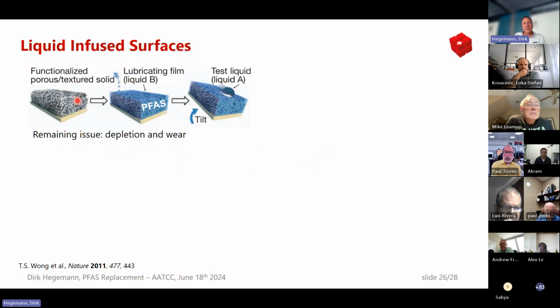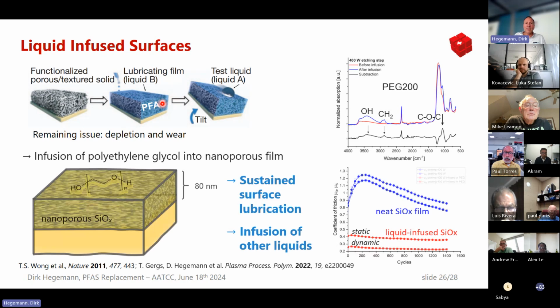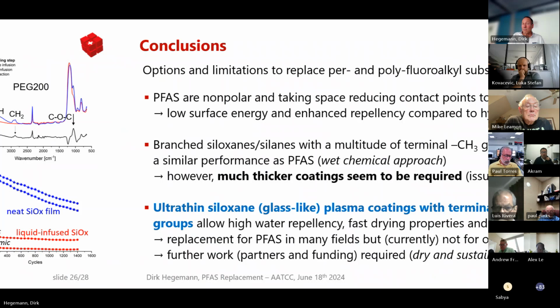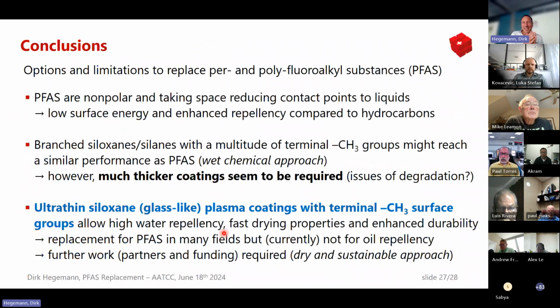But it shows maybe some potential to look at liquid-infused surfaces. Also here you are using a porous textured surface. Nowadays, it's still PFAS that are used to be immersed into the structures, and then you have highly repellent properties. However, to replace PFAS, you can immerse other substances. We could show that we have hydrophilic substances immersed in a nanoporous plasma polymer, which shows a much higher durability. You have less depletion. And for example, here shown with the lubricating silicone oil, you have permanent low friction properties. And now from this, one might start to infuse with other liquids to go more towards oil repellency. So this is just a few ideas I'd like to give of where it might go. Definitely there's research needed. And with this, let's see what we can discuss after my talk.